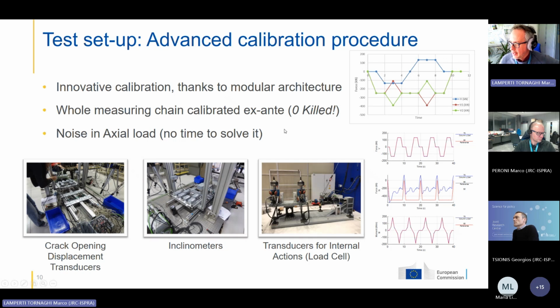Before the testing, the real-scale testing, we calibrated all the instruments and the whole measurement chain. This required us to design an innovative calibration kit for the load cell. You see here a load cell alone tested with this system, and we also tested the inclinometers and the crack opening displacement transducers before the test. Here you can see the evaluation of this.